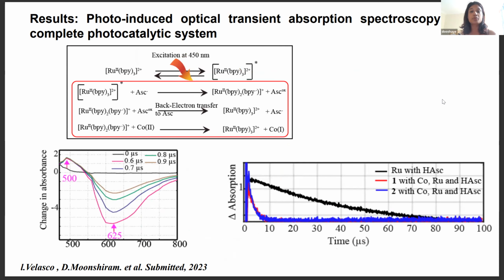Following the time-resolved measurements for the cobalt-2 formation, we also carried out optical transient absorption. So upon light excitation, we see a very broad band, which typically corresponds to the fluorescence of the excited state of the ruthenium photosensitizer. And this photosensitizer, in the presence of the ascorbate electron donor, forms the reduced ruthenium species, which has a broad absorption band of around 510 nanometer. And in the presence and the absence of the cobalt catalyst, the kinetics are largely different. So in the presence of the cobalt catalyst, we see that it decays very rapidly. It has an 18-fold enhanced decay back to the ground state, which shows that the predominant quenching pathway in this family of catalysts is the reductive quenching one.